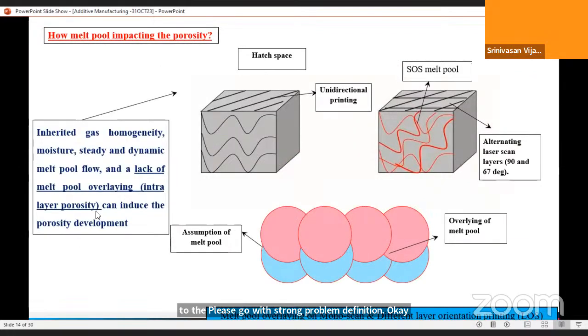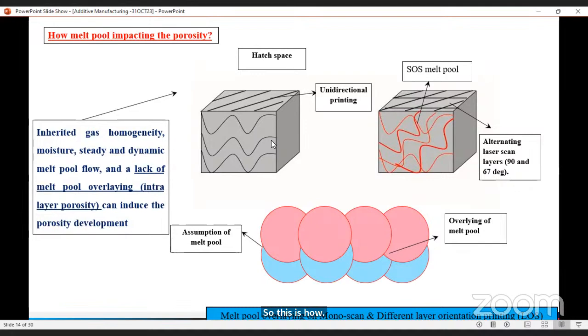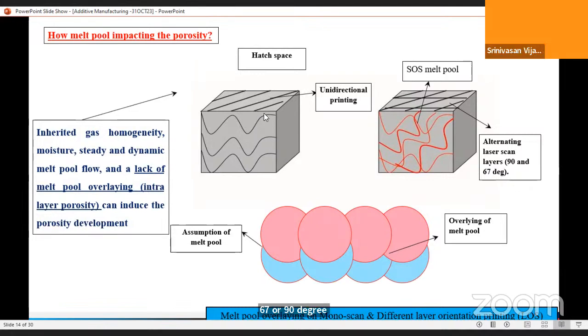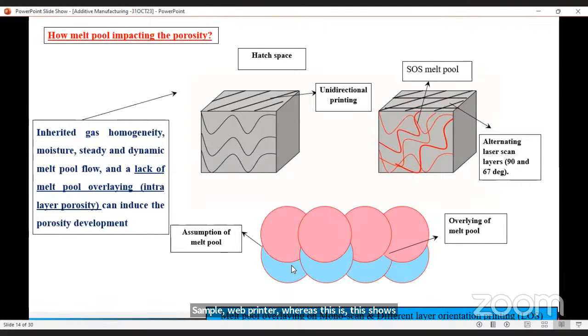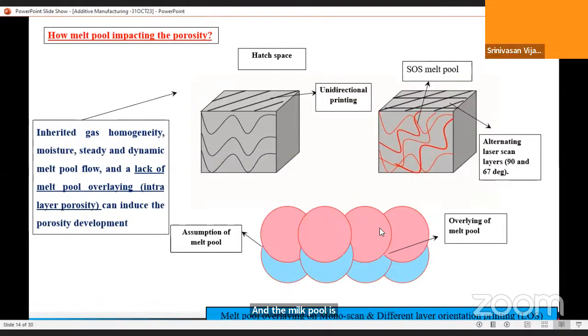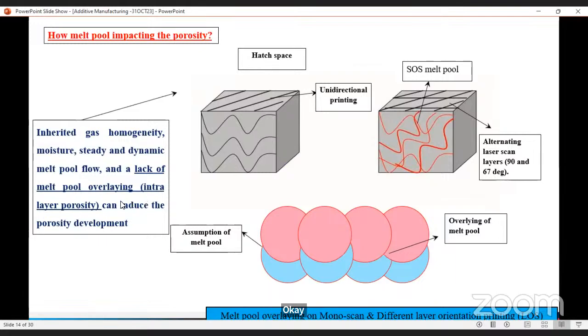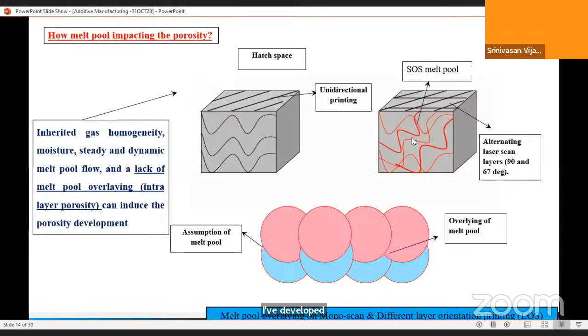So this is how 67 or 90-degree samples were printed, whereas this shows alternating laser scan of 67 and 90 degrees, and the melt pool is overlapped like this, overlaying of melt pool like this. So what happens? Inherited gas homogeneity, moisture, steady and dynamic melt pool flow, and a lack of melt pool overlaying can reduce the porosity. Okay, it reduces the pores in the case of hybrids.